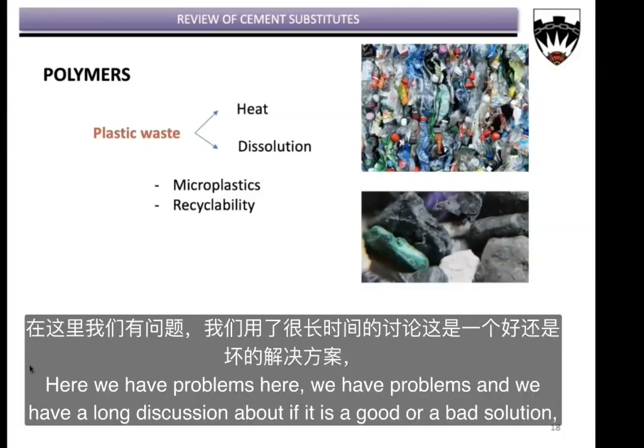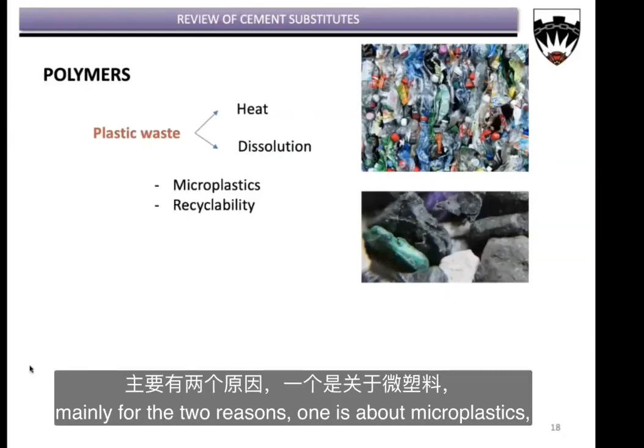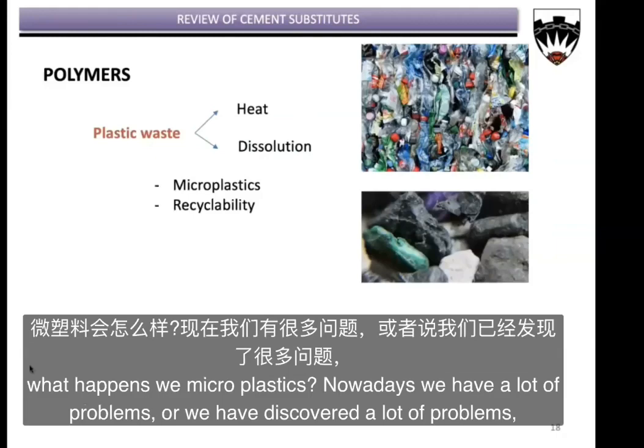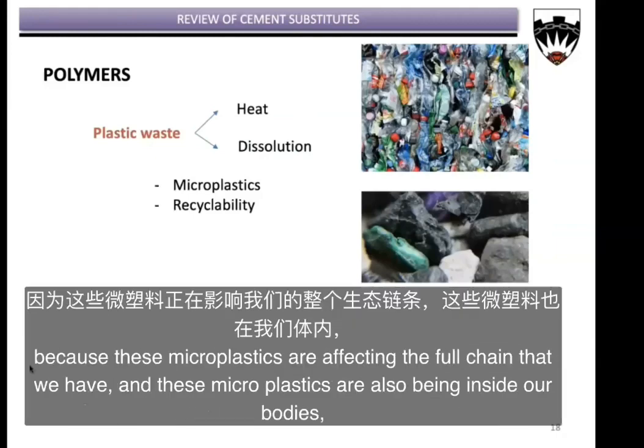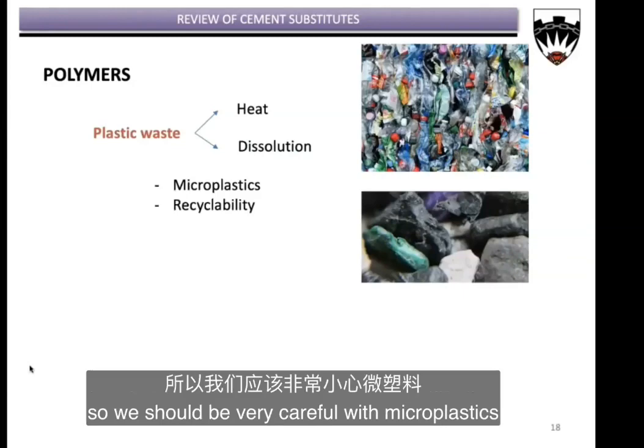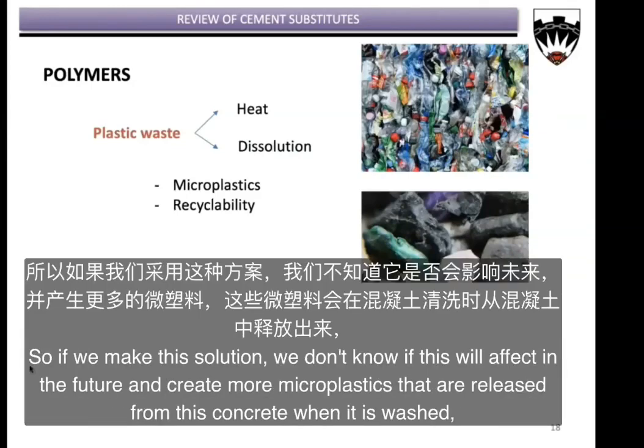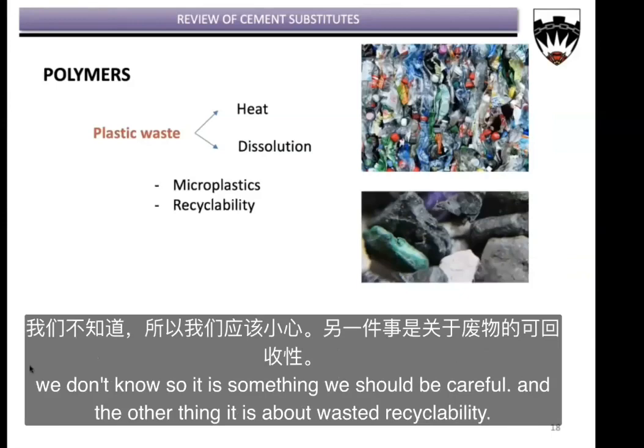Here we have problems. And we have a long discussion about whether it is a good or a bad solution, mainly for two reasons. One is about microplastics. What happens with microplastics? Nowadays we have discovered a lot of problems, because these microplastics are affecting the food chain that we have, and these microplastics are also being inside our bodies, right? So we should be very careful with microplastics and measure them. So if we make this solution, we don't know if this will affect in future and create more microplastics that are released from this concrete when it is washed. We don't know, right? So it is something we should be careful about.